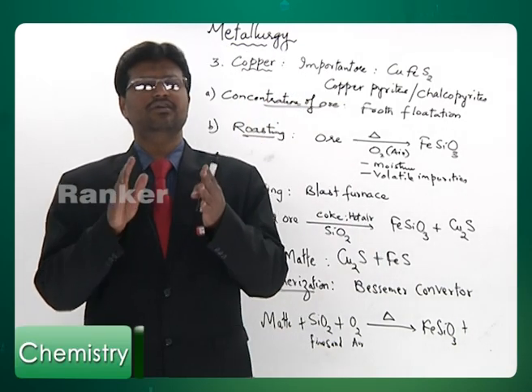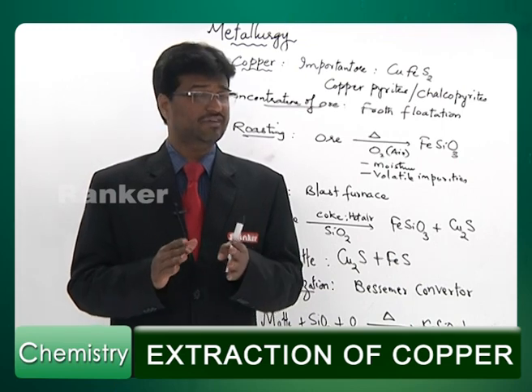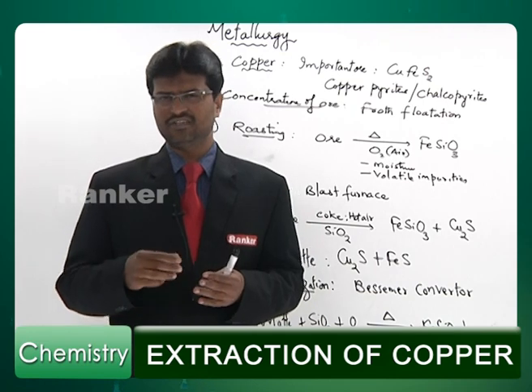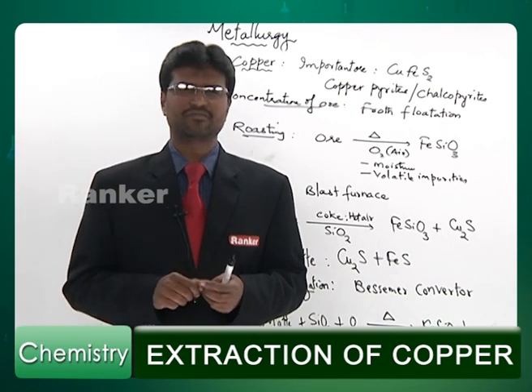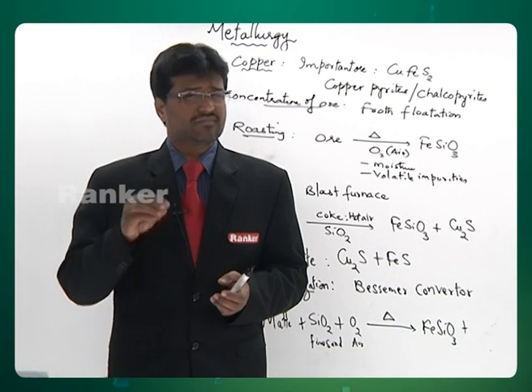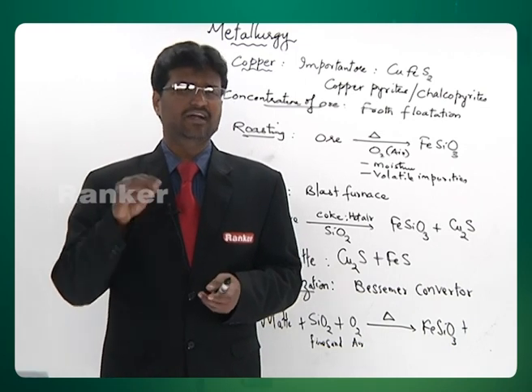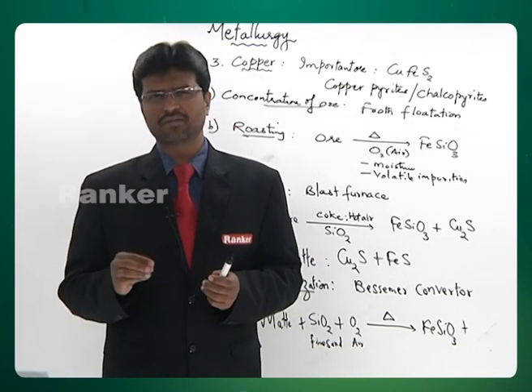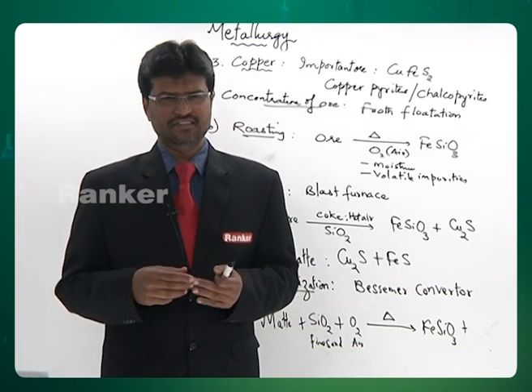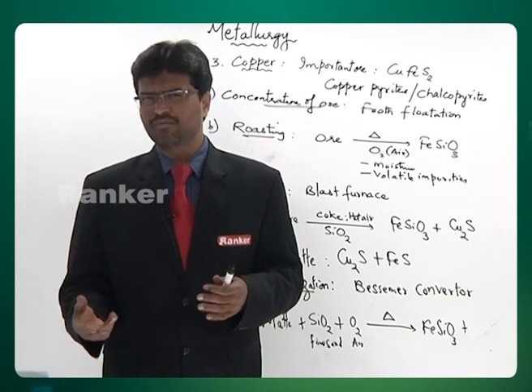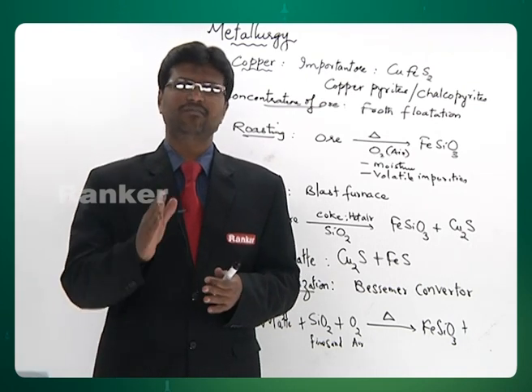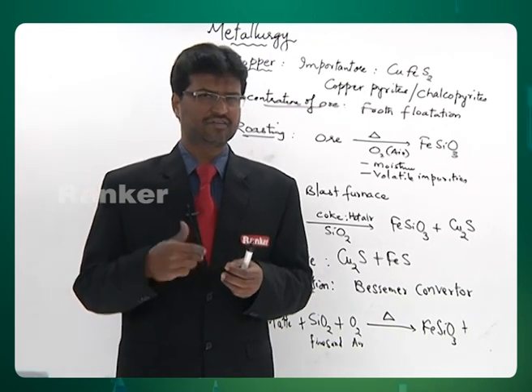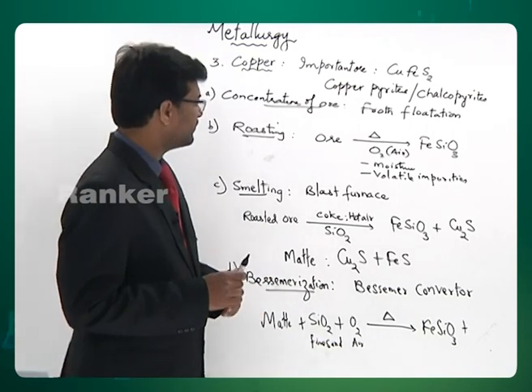When you cut the supply of sand — which you do when the colour of the flame at the mouth changes, since it burns green as long as Fe is present — then continue heating and passing air. This oxidizes some of the copper sulphide to copper oxide. When sufficient copper sulphide has been converted to copper oxide, cut the supply of air and continue heating. Auto reduction then takes place and you get copper.